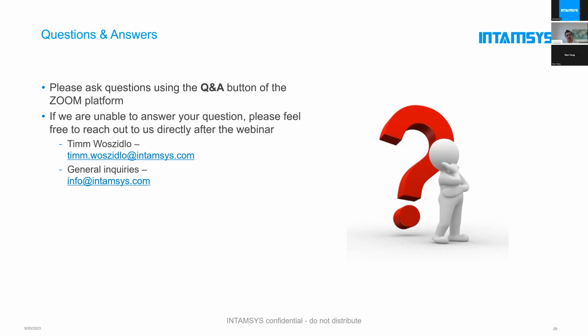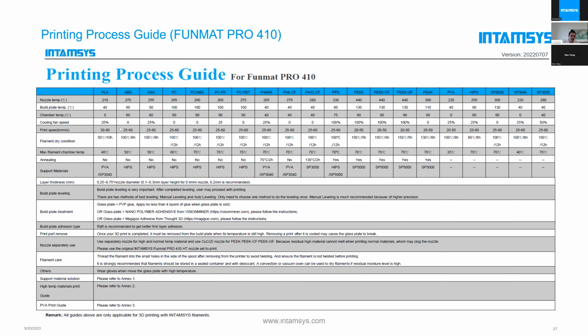And drying is really key. Yeah, because I would say if we say 80-degree 12 hours, then you should do 80-degree 12 hours, not 100-degree 6 hours, not 60-degree 24 hours. You need to stick to the time, you need to stick to the temperature to achieve the dry result that you want to have. And what we can say is if we look back into our process guide, is that we have the drying conditions specified for all of our materials, and all of them are moisture sensitive, some less, some more, but all of them have some moisture sensitivity. So it's really important to keep materials dry and to dry them actively.